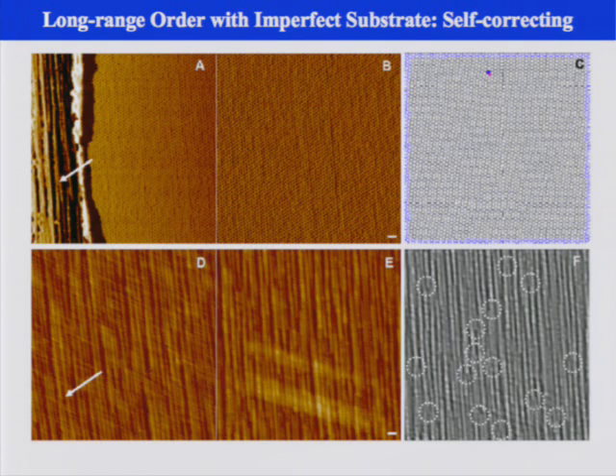So what this says is that even though the underlying substrate has defects, and the defect density can be fairly high, by coupling the single crystal of the inorganic material together with a self-assembled block polymer, you can indeed generate this nanostructured thin film membrane or block polymer thin film with really good long-range order.